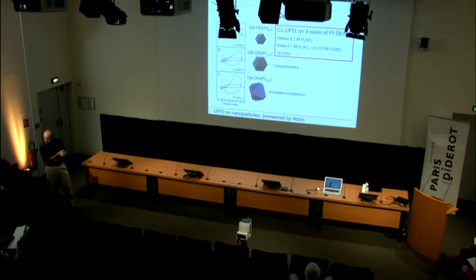And this is well known from the bulk platinum copper UPD literature. And why not here? Well, it's because there's not much of a facet on these small ones. The facets are just a few atoms, and so it's not really a facet. It has a lot of character of edge atoms and corner atoms. Okay, so this is what we believed when we saw these voltammograms. That's the way we interpreted them, very qualitatively.